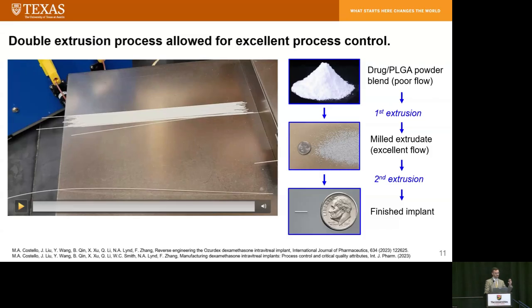So in the first extrusion, we force this fluffy powder through the extruder, and then take that extrudate from the first run and mill it into granules. So these large granules have a much larger particle size and have much better flow. Then we do a second extrusion using that milled material, and that milled material has excellent flow properties, so the feeding works great, and as a result, the extrusion process is very consistent, and then it's possible to have excellent control on the implant's diameter and other properties.